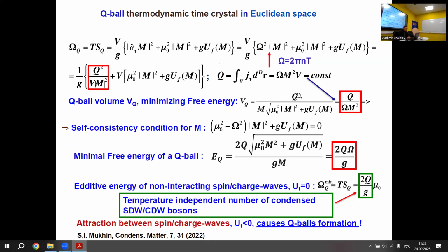And then when you use this relation again, you can write this equation. So you see that the Q charge cancels and you get a self-consistency equation for the M field. So indeed, it depends on the parameters, on these coupling strengths between fermions and say phonons or spin waves, and on this bare correlation length of these fluctuations of the lattice or spin fluctuations.